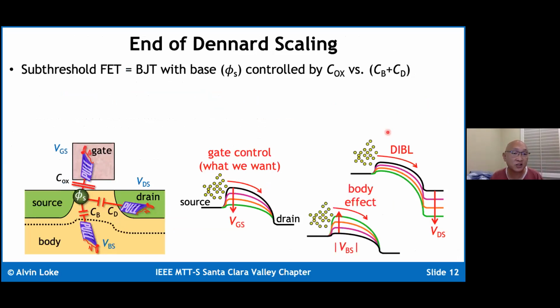Okay, so that lasted for several generations, and it was clear that even moving into 32 nanometers, we were running into an issue where a lot of these transistors were becoming more and more difficult to scale because the transistor was having a difficult time to shut off. Okay, how can we view that? Well, you can think of a transistor in subthreshold essentially as a bipolar transistor, where the surface potential, analogous to the base in a bipolar, near the source of the device is really controlled by a tug of war between COX, which is what you want to control, but it's got this parasitic body and drain coupling that basically prevents the gate voltage from tightly coupling the surface potential up to the gate.